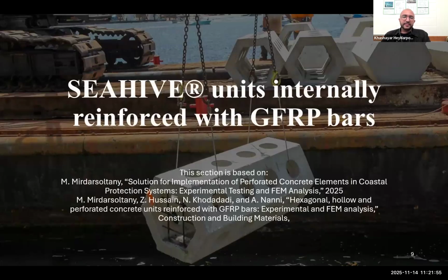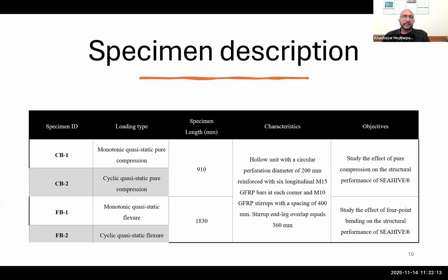One of the first studies that was conducted on SEAHIVEs were the units internally reinforced with GFRP bars. The credit of this work is majorly for Mirdarsoltany during his PhD studies. In this study, 4 specimens were tested. 2 of them, CB1 and CB2, were under pure compression, and the 2 other SEAHIVE specimens were under 4-point bending.